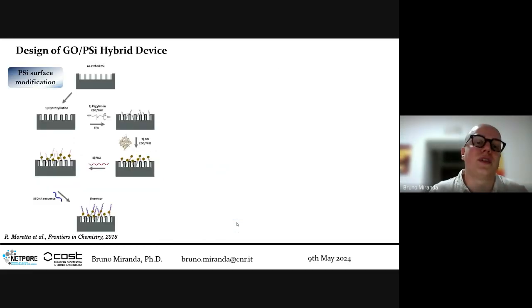The surface modification is the one I showed before. You have the SH, the porous silicon, you hydrosilylate, pegylate, and then functionalize covalently with carbodiimide chemistry the graphene oxide on top of the surface, and immobilize PNA on top of the graphene oxide. Finally, you make the PNA interact with the DNA, and you obtain your final device.